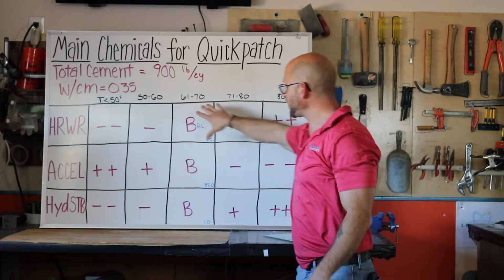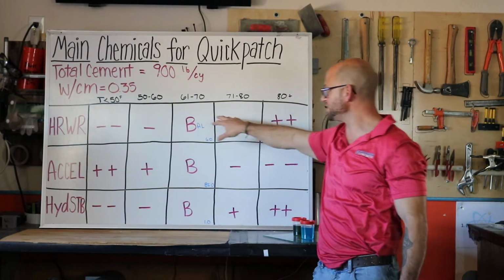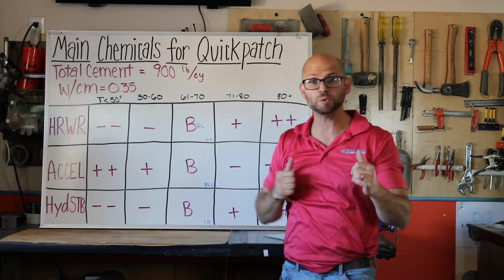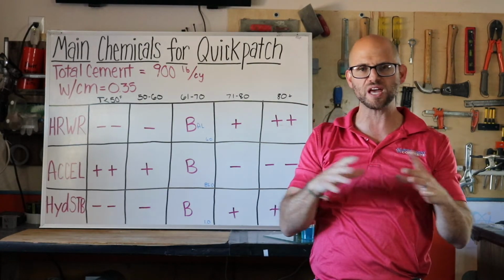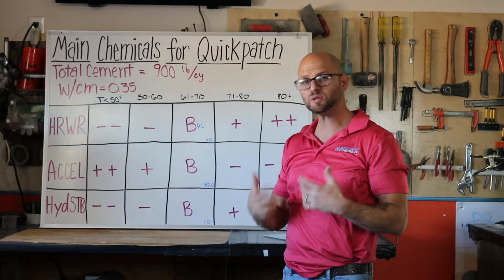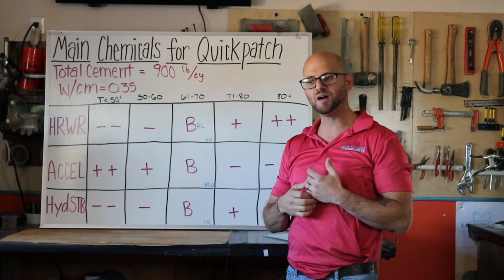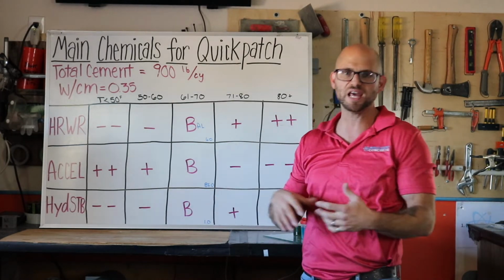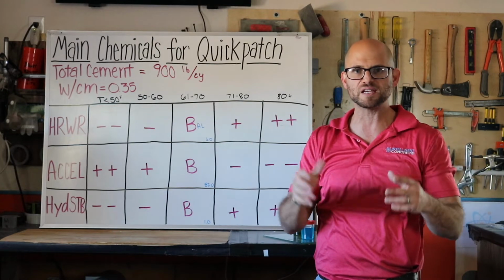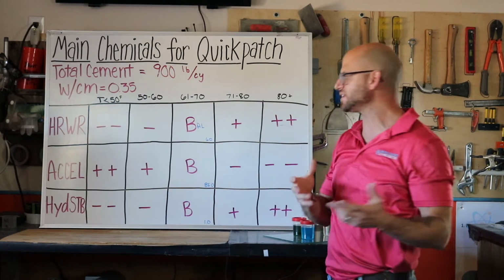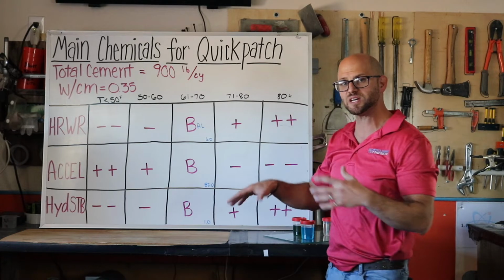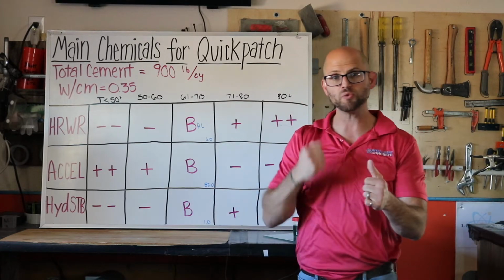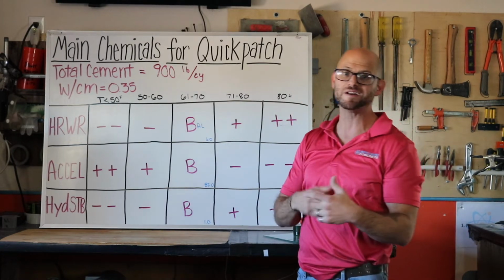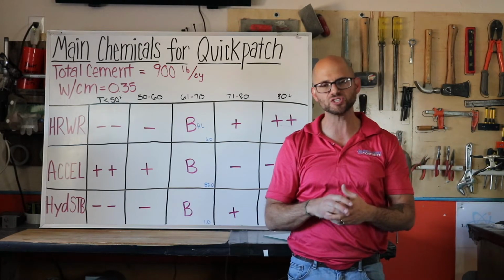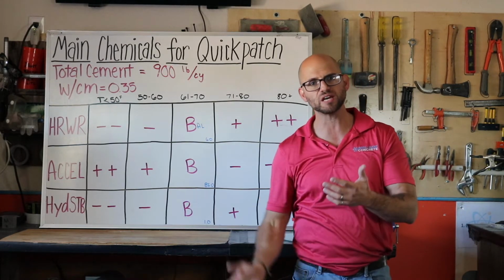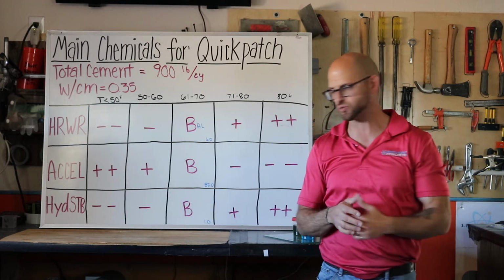That being said, when I increase my temperature from this balanced state, I've got to put more high range water reducer in to get me that fluid flow, because normally when we get a hotter mix, we see those hydration kinetics start taking off and monopolizing that high range water reducer and that tightening. So a little bit more high range, because we're so hot, I can ratchet back half a step on my accelerator.